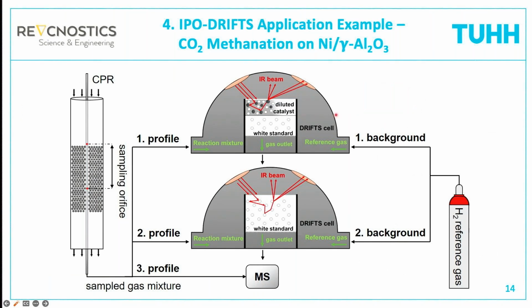And to do this, we ideally do 4 profile measurements. In the first measurement, we fill the DRIFTS cell with the highly diluted catalyst and send our reaction mixture that we take from the profile reactor into the DRIFTS cell. And in this case, we can do the IPO-DRIFTS profile measurement. And then we do the measurement with the background gas, which in our case was hydrogen, because hydrogen is IR silent. And it is already present in a large concentration in the feed. So it's a very good reference gas to put our catalyst in a reference state to which we can refer all the absorptions that we see.